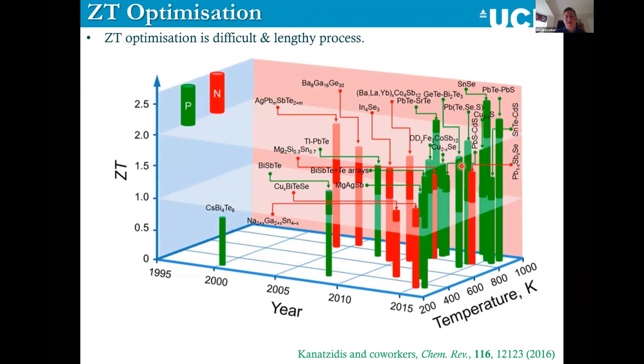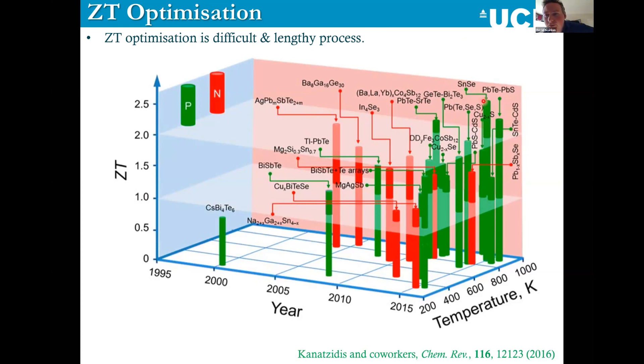The ZT record for conventional materials — shown in a diagram by Kanatzidis and co-workers — has just broken through ZT = 2, with a world record for tin selenide around 2.4–2.6. However, all record-breaking materials are P-type; N-type materials lag at about 1.5–1.6 and all contain either toxic materials like lead or rare materials like tellurium. This has driven great interest in oxide thermoelectrics: they are cheap, earth abundant, non-toxic, and stable — though currently they don't perform very well, with only two systems ever exceeding ZT = 1, both P-type.